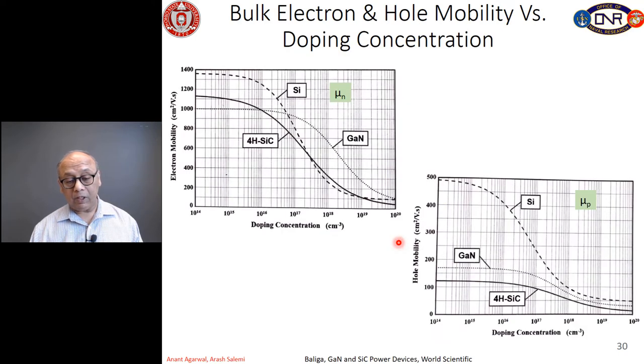All right, so here is a chart comparing electron mobilities for different materials. In this case, we have silicon carbide, which we call 4H silicon carbide, a particular type of silicon carbide which we will describe later. And then we have a material called gallium nitride, which we will also describe later. Collectively, if you remember, we described silicon carbide and gallium nitride as wide band gap materials. And then we have silicon here. You can see the electron mobility as a function of doping concentration for silicon, silicon carbide, and gallium nitride. Silicon has the highest electron mobility up to this point, and then silicon carbide is slightly better than silicon, and gallium nitride is a lot better than silicon at higher doping concentrations.